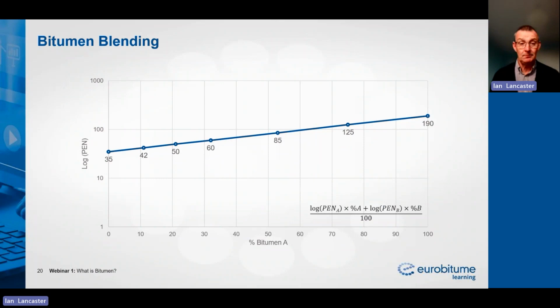Now, it is possible to operate that distillation column to produce every single grade of bitumen that you may want to produce. But in this respect, bitumen is actually quite a forgiving material because you don't actually have to do that. You can take hard bitumens and soft bitumens and blend them together to give you intermediate grades. Now, as you can see on the graph here, we can blend from our 35 penetration up to 190 penetration, and we can produce those intermediate grades there.